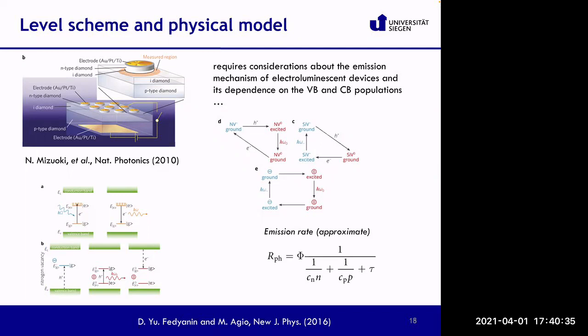in the valence band. So then to be able to get electroluminescence, you need to create electron and holes in the conduction and valence bands of diamond. So it means that you have to dope diamond, because we know that diamond is not conductive. So this is the first problem. The second problem, you have to make sure that this doping is effective, so that it is not giving a small number of electron and holes. And this is also a big problem, because defects in diamond are basically trapping electron and holes.